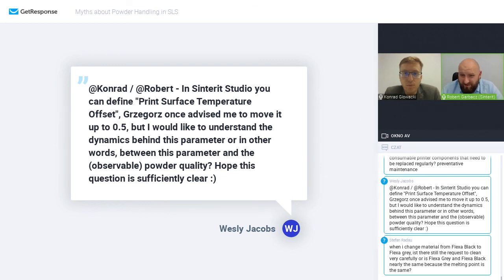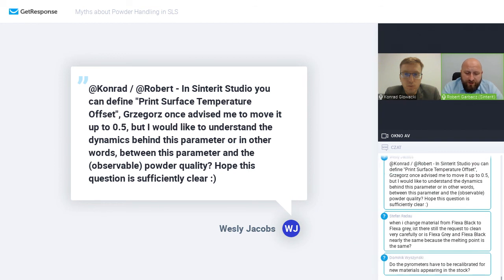And we've discovered that it's quite a rare thing to raise the temperature by 0.5 from the beginning, especially when the room is not at the same temperature at which we calibrate the machines. Let's start from that. We calibrate our machines at room temperature, let's say 21 to 24 degrees. So, for example, during the hot summers, the temperature in our calibration chamber, imagine 50, 60 printers printing at once, and even with air conditioning, is a little bit higher.